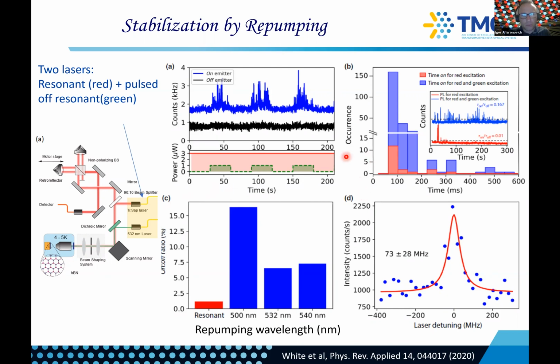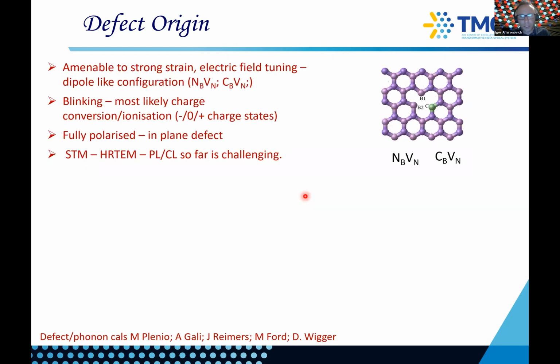Yeah. So the main question that we are basically trying to address through all these studies is, what are these emitters? And it's a needle in a haystack problem. Just our needle is not that big. And so here there are a few examples of a lot of theory work on what it can be. Our initial hunch was some sort of a vacancy-based defect, and then a recent theory suggests that vacancy-based defects would result in a very broad emission. So it is unlikely to be the case. But it is fully polarized, so it should be an in-plane defect, and also most likely some sort of charge conversion. So one of those charges, probably more likely.